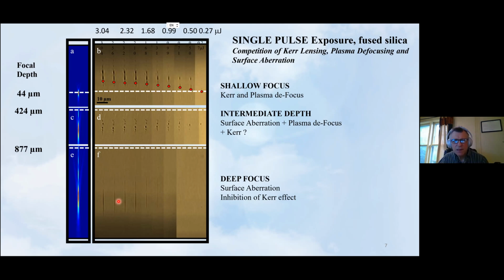So now when we increase power from low pulse energy to high pulse energy, you get to a threshold of nonlinear absorption. So at low energies, nothing happens. And here is the first beginnings of modification. And these are refractive index changes made with a single pulse. So deep here in the material, we're seeing the effects of surface aberration.